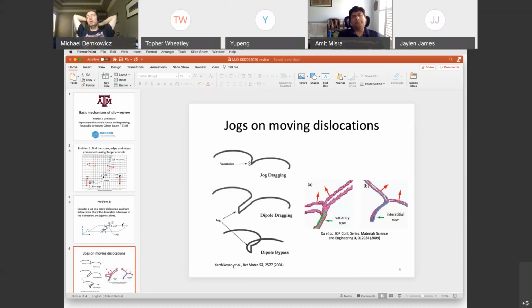I guess you don't have to be at the level of shock loading to generate point defects by jog drag. For example, in uniaxial tension tests, when you're approaching failure via necking, generation of a large number of point defects by jog drag is hypothesized to contribute to the nucleation and growth of voids leading up to failure by void growth and coalescence.